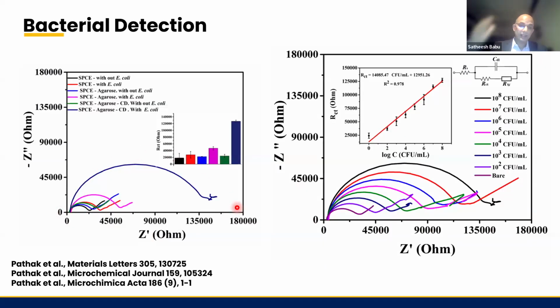And also we tested that particular electrode for various concentrations of bacterial sample. And we found that this sensor electrode was able to detect the entire range of concentration starting from 100 CFU to 10 to the power 8 CFU per ml. So this is 10 to the power 2, that means 100. These are the clinically significant bacterial load. So this sensor system was able to detect even such lower concentrations of bacteria without any culturing of the sample. What we have done is just took the sample, just introduced the electrode, and then tried measuring the impedance.